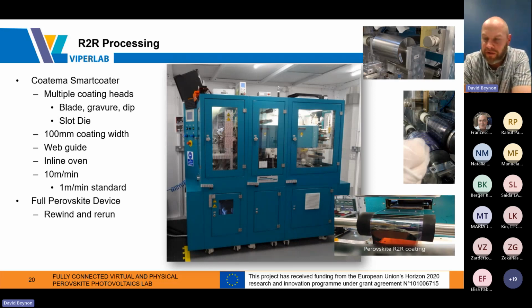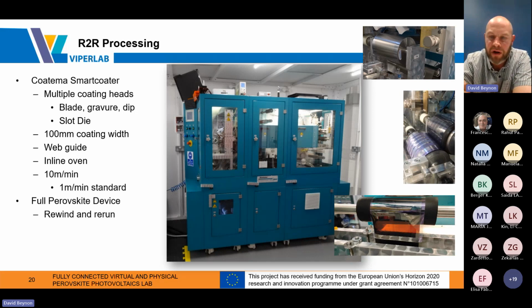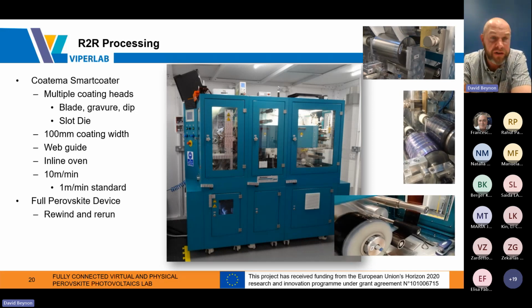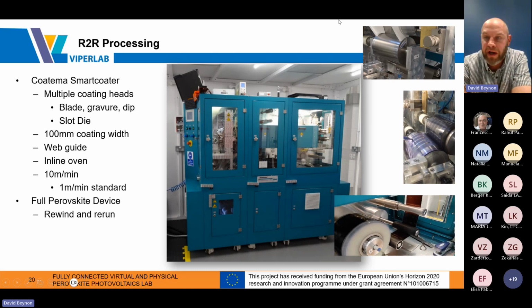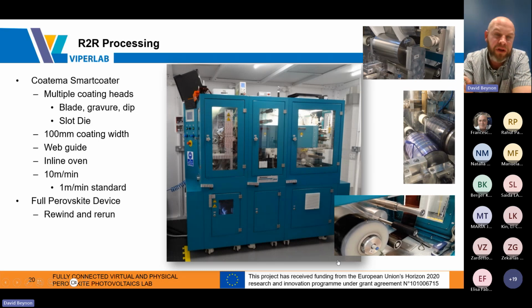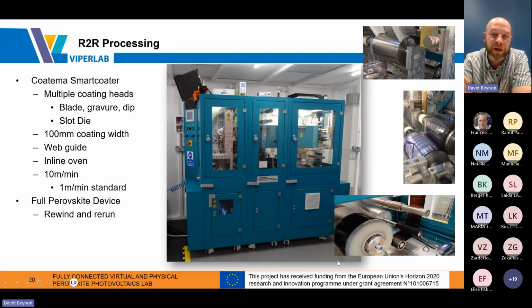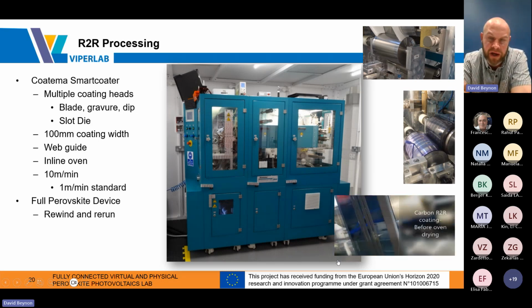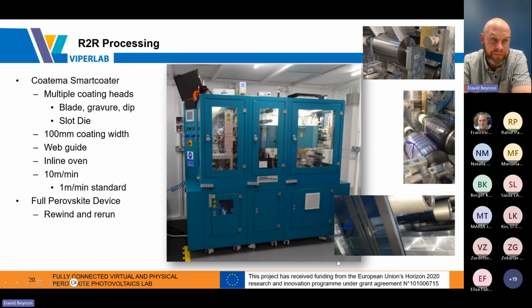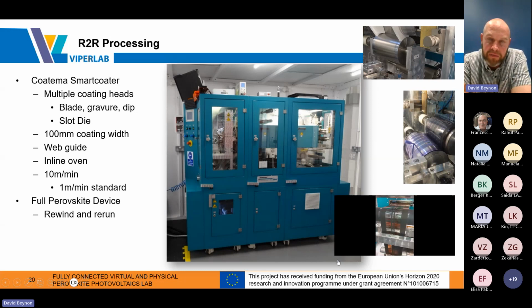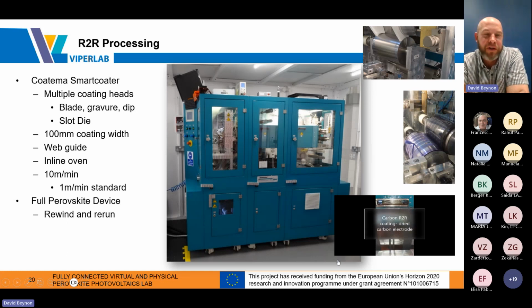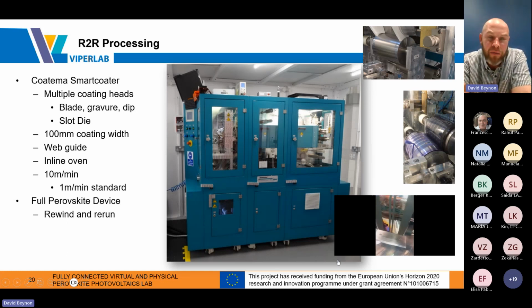Okay, so the final bit of infrastructure would be our roll-to-roll scale-up to our pilot scale coating facility. So this is our Coatema Smartcoater. We have multiple heads, so we have blade coating, gravure coating, but principally we use slot die coating. This is set up within our clean room, so it's in an ambient atmosphere, but a humidity controlled environment. We have 100mm coating width, could say infinite coating length, but we typically put 150 meters of substrate in. We have an inline oven, which is 2 ovens, but it's in total 1 meter long. So we can coat up to 10 meters a minute. We typically coat at 1 meter a minute just to standardize our drying at 1 meter residence time.